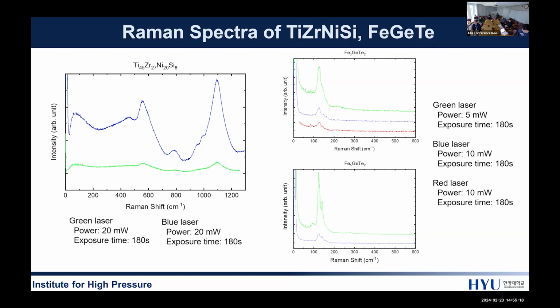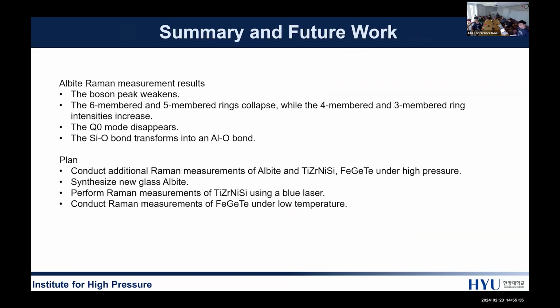The titanium zirconium sample had good resolution with the blue laser, and the iron germanium tellurium shows good resolution with the green laser. This is my summary and future work. I synthesized the albite and conducted Raman measurements applying pressures from ambient to 20 GPa.